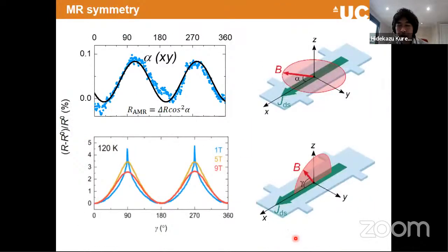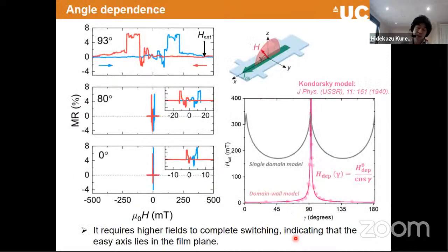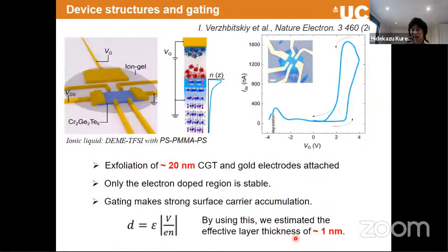But then for our case, I think there's a question of what this ion or ionic gel does at the surface, but this is something we cannot observe locally. So unfortunately, I don't have a clear answer to that, but I'm slightly optimistic that it doesn't do much, except for one thing that I mentioned: there's a chemical reaction when you dope or when you apply the negative voltage. In this case, there's a chemical reaction happening at the surface, but on the positive voltage side, this doesn't happen. So we wish that the main effect is simply charge doping or charge accumulation rather than any other chemistry.